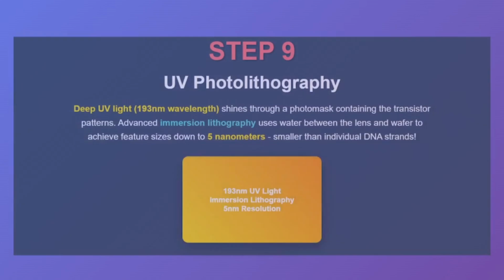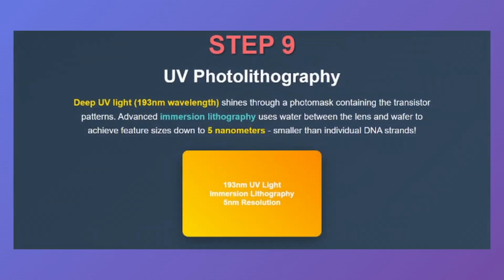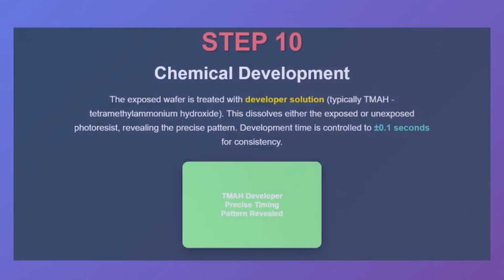Step 9. Photolithography. Deep ultraviolet light, just 193 nanometers in wavelength, is projected through a mask onto the wafer. Immersion lithography, using a thin layer of water, enables feature sizes as small as 5 nanometers, smaller than a strand of DNA.